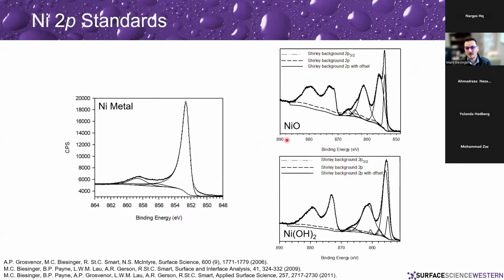But if we look at our two different, say, common nickel 2 species, nickel 2 oxide and nickel 2 hydroxide, you can see that the shapes of these peaks are very, very different. And so even though they're both nickel 2, we're not going to look at these systems and just say, okay, I have nickel 2 or nickel metal. We're going to say, okay, I have nickel 2 oxide, or nickel 2 hydroxide, or nickel 2 sulfate, or whatever it is. But you can pull out individual species very well because of the shapes of these things. And so we model all these sorts of things.